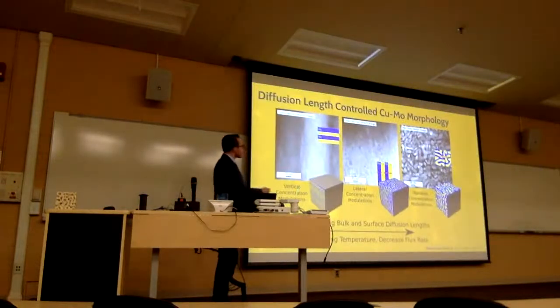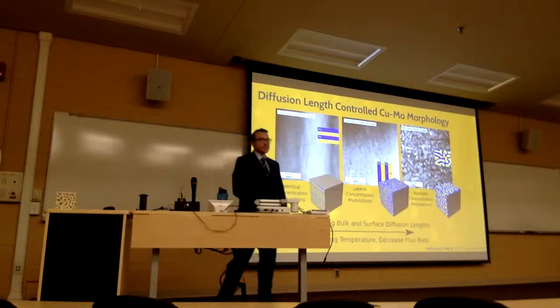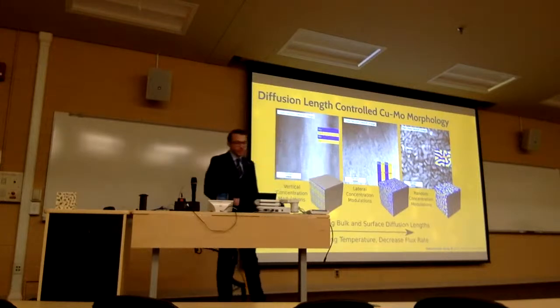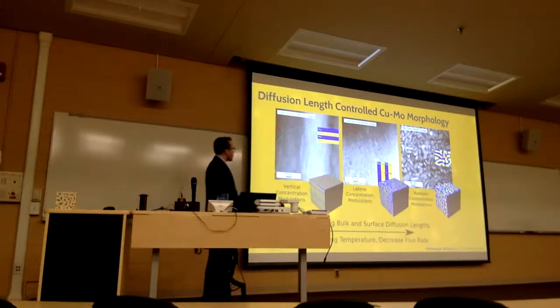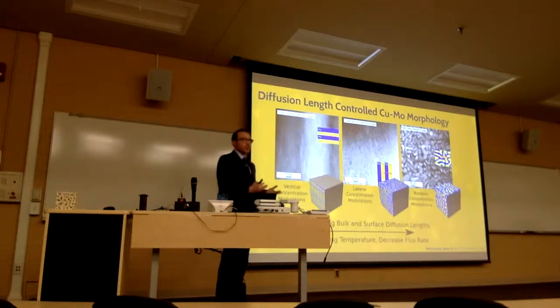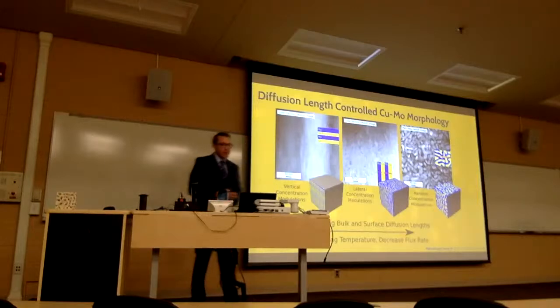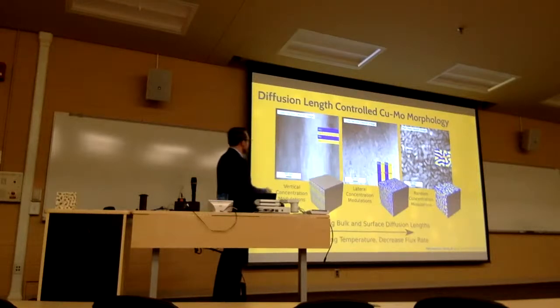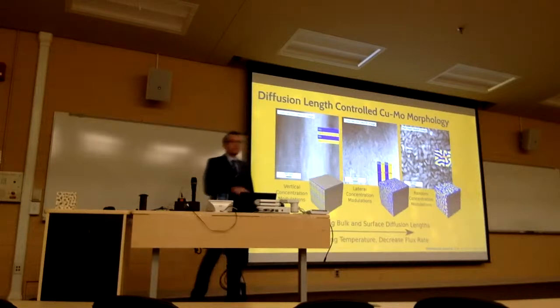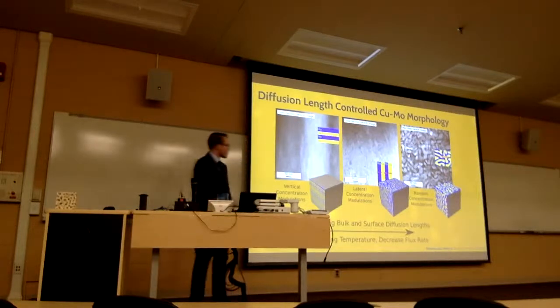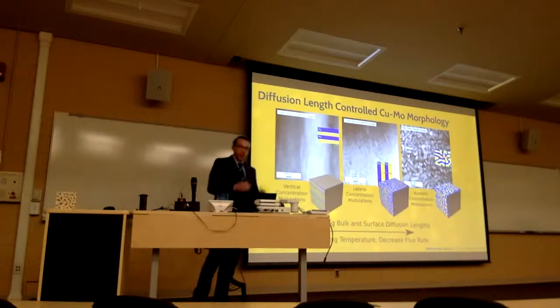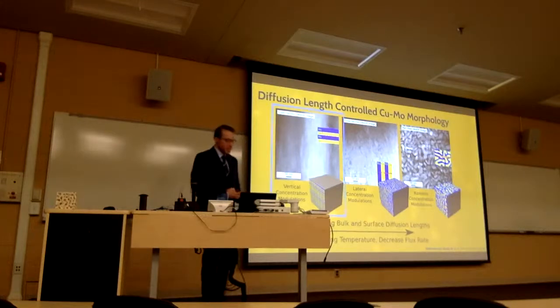And I'd like to share with you a summary of those thin film architectures that we designed using this process. So these are all atomic number contrast images, where we can see copper is darker in this sample, and brighter regions represent the moly-rich domains in the structure. You can see the length scale of these three morphologies and how the concentration is evolving as a function of the deposition conditions labeled here. So you don't have to take this all in because we'll describe them each in turn.